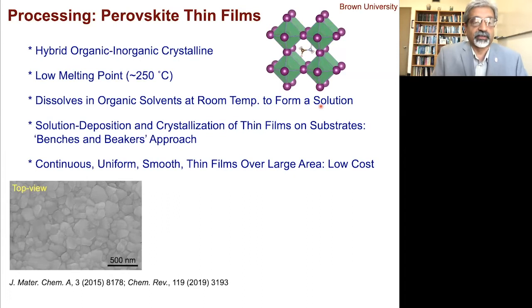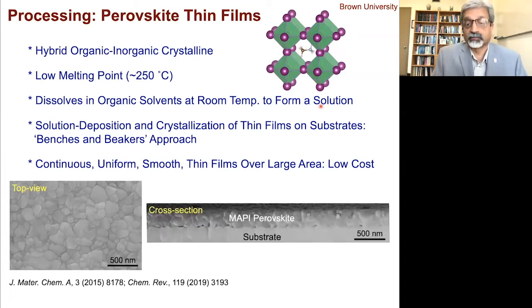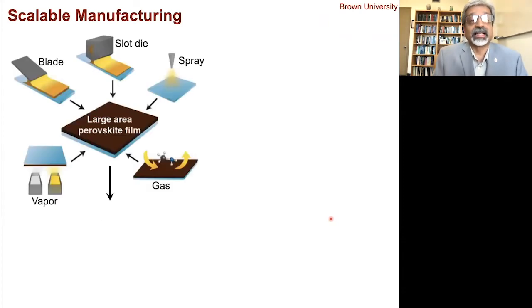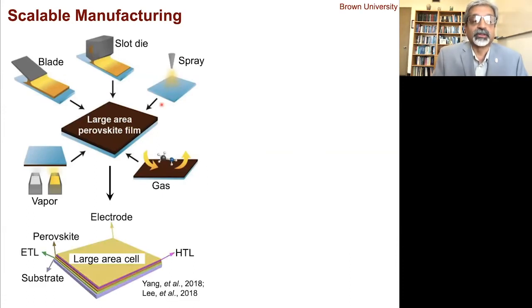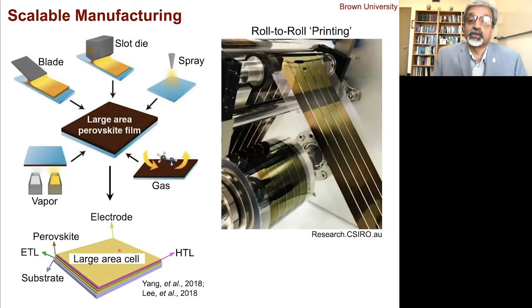And here's a picture of a top view of a thin film made in our lab. And this is a cross-section of a thin film made in our lab. As you can see, it's quite thin, about 500 nanometers or so. So people have been working on scalable manufacturing of this, of course, because we have to make this into large areas. There are several methods used, and then you make large area solar cells out of it, right? And you can also use roll-to-roll printing to make solar cells very cheaply and fast.